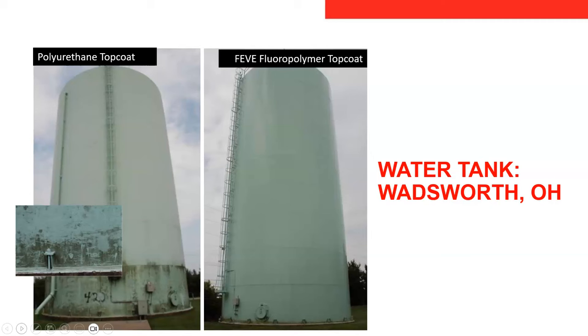The one on the left was the previous film, which is a polyurethane, and that was then overcoated when it came to the end of its life with a fluoropolymer top coat. And we're happy to report that the fluoropolymer is performing much better. They're not seeing the same type of severe mold and mildew issues that they were before. And again, just a testament to, I think, the cross-linked density of the fluoropolymer film itself that's resisting a lot of that growth.